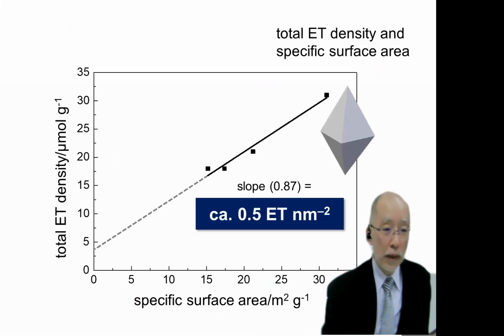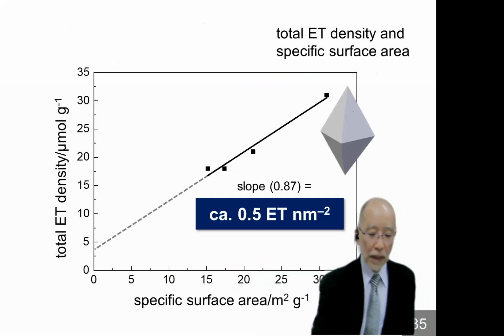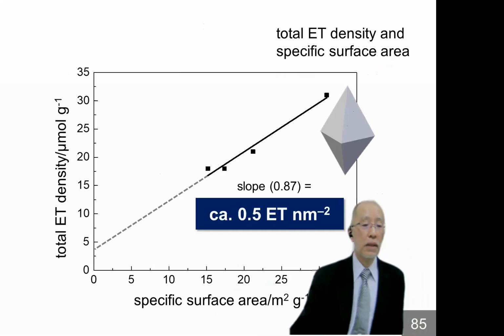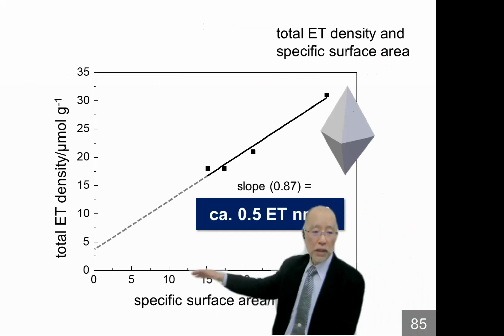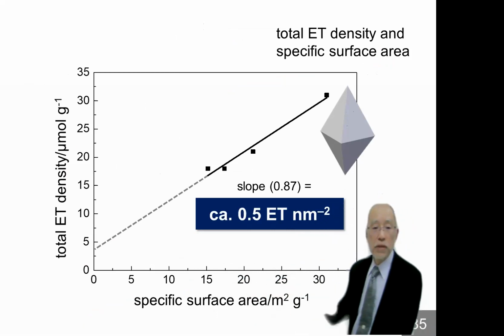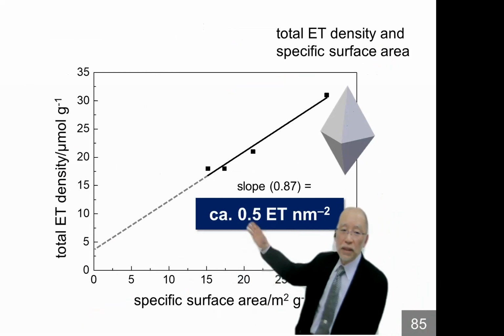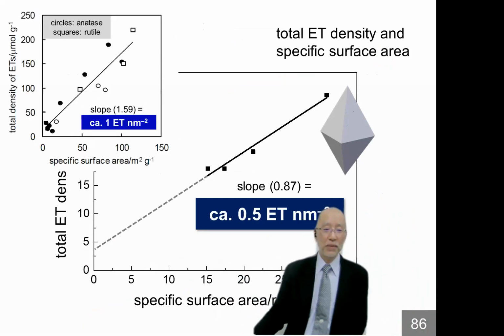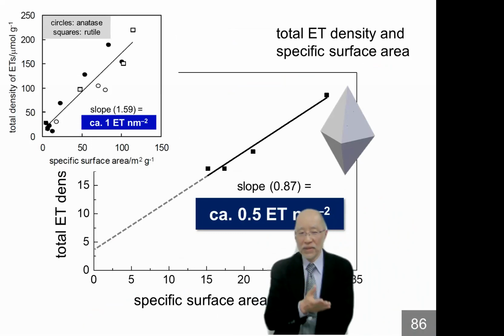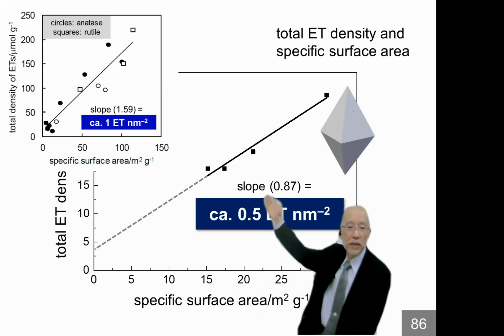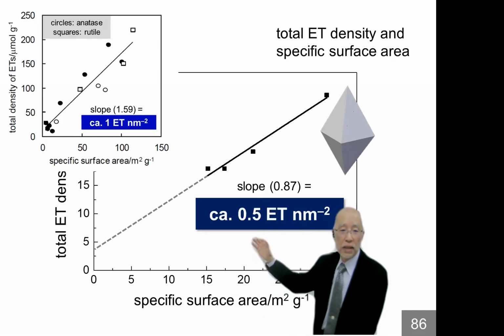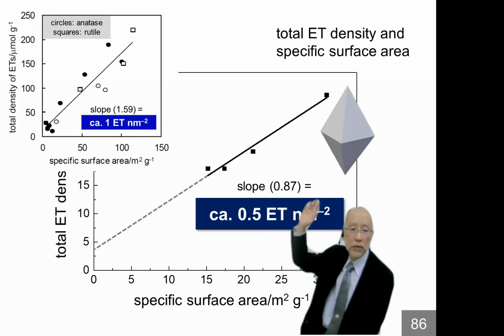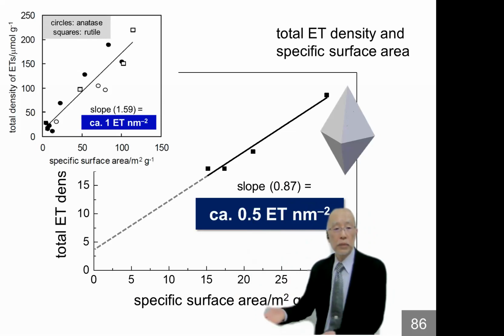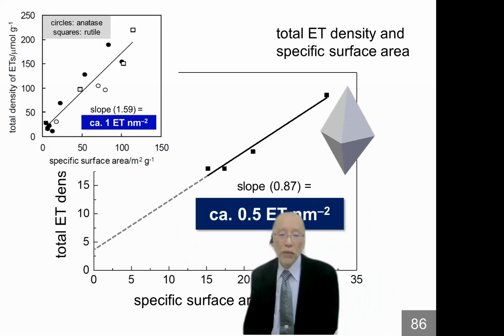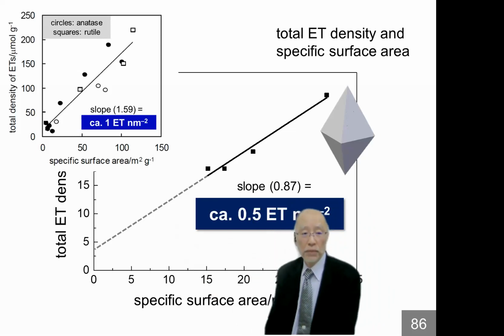And an important point is the particle size dependence. Sorry, before that, this is the total electron trap density plotted against the specific surface area. And a very good linear relation. For the commercial titanium oxide sample, it was impossible to say a very good linear relation. But for octahedral particles, that is a very, very good linear relation. And the surface density of electron traps for this octahedral particle is about 0.5. That is almost half of that of a commercial titanium oxide sample. And the 101 facet may have a lower density of electron traps on the surface.